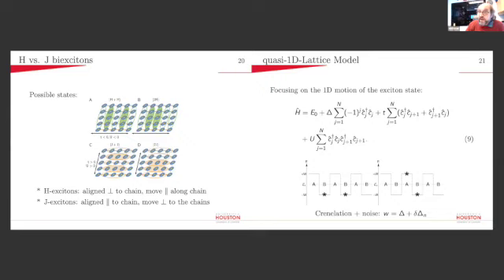If I look at the bottom pane of that figure, I can have an unbound pair of excitons. The little stars are the excitons, localized on site B, for example, and those would be an unbound pair. The contact interaction U turns on if I have excitons on an adjacent site, either on site A and B or BA, it doesn't matter. But two excitons on non-adjacent sites are considered non-bound within this very simple Hubbard model. We have not done the two-dimensional version of this, but it's relatively straightforward to adapt.